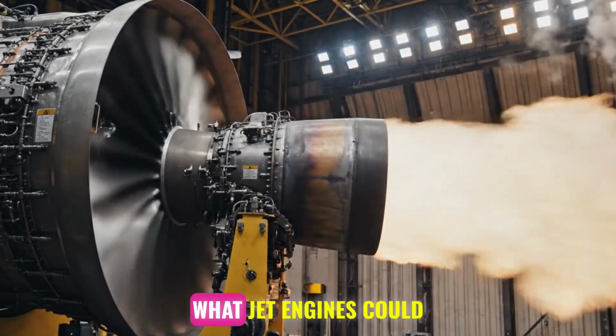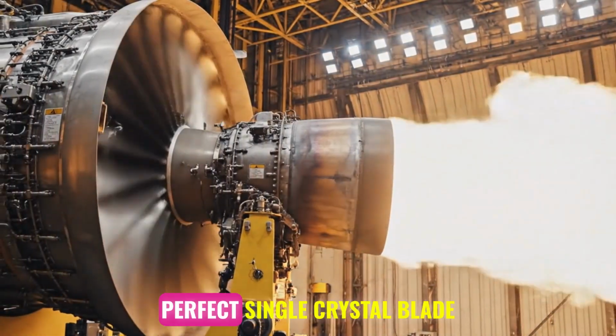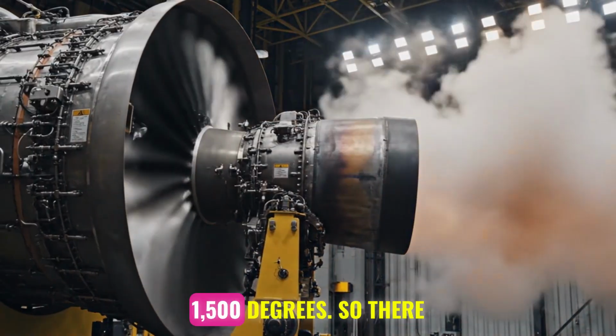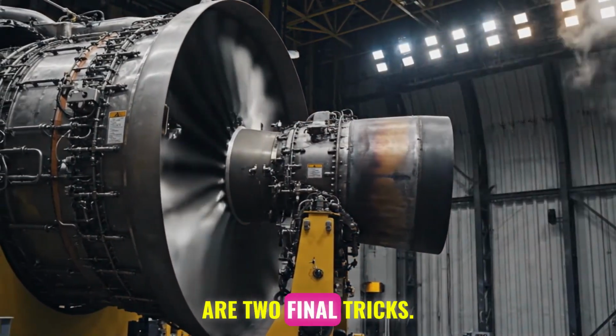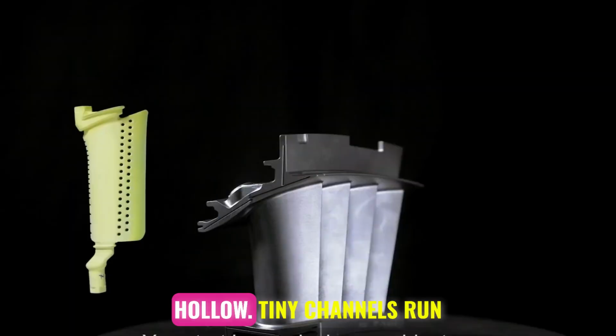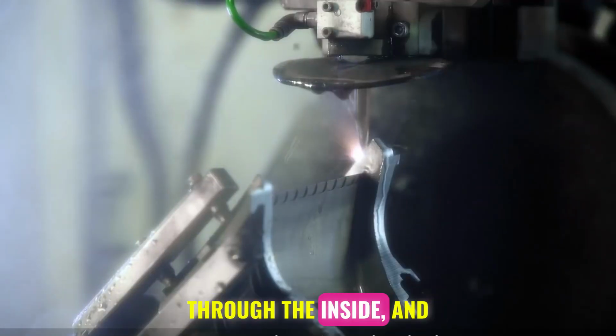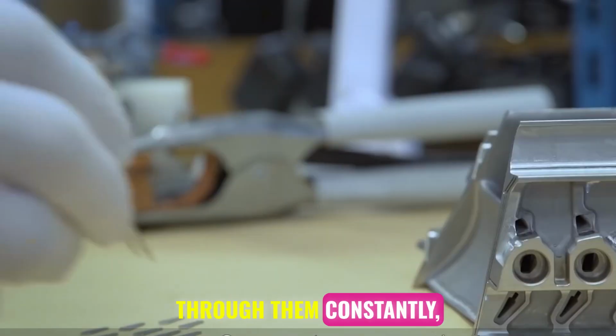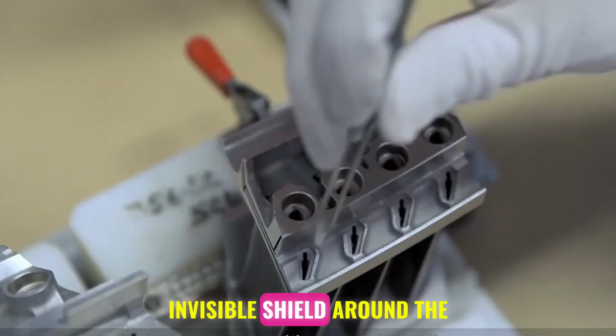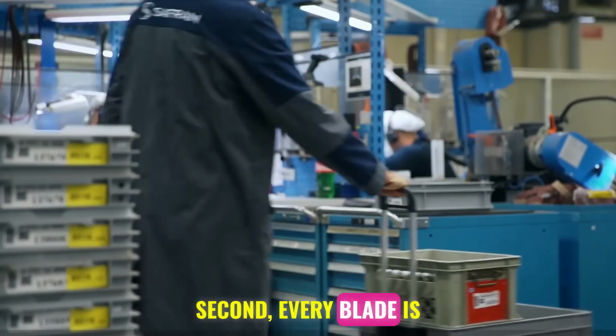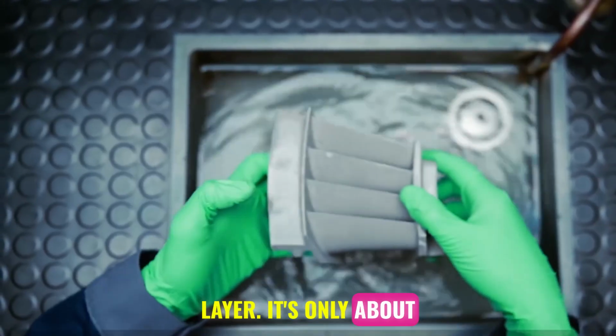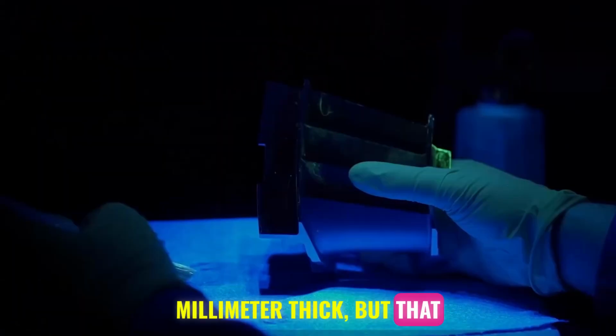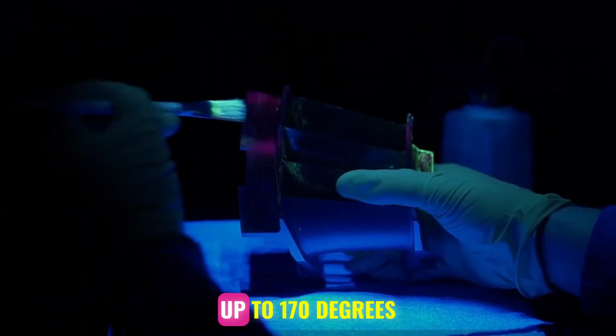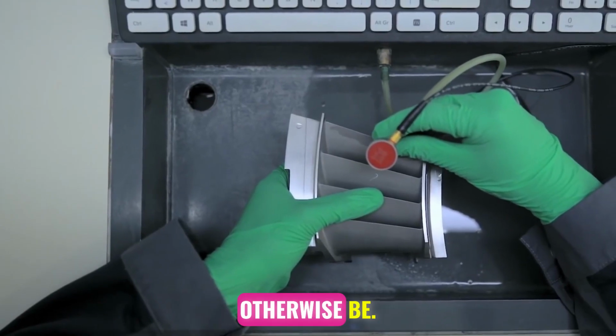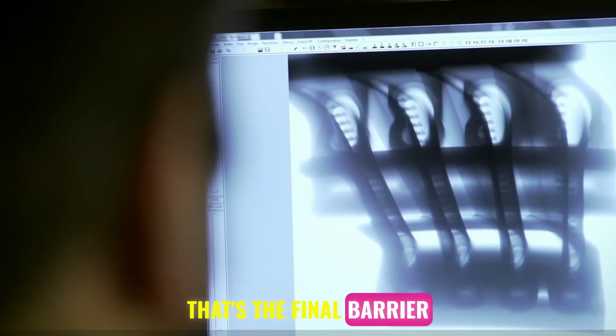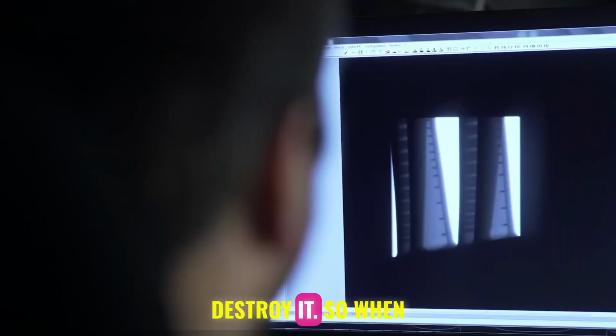That completely changed what jet engines could do, but even a perfect single crystal blade would still melt at 1,500 degrees. So there are 2 final tricks. First, the blade is hollow. Tiny channels run through the inside, and cooler air gets pumped through them constantly, acting like a cool invisible shield around the blade. Second, every blade is coated with a ceramic layer. It's only about 1/4 of a millimeter thick, but that tiny ceramic coating keeps the metal underneath it up to 170 degrees cooler than it would otherwise be. That's the final barrier between the blade and the heat trying to destroy it.